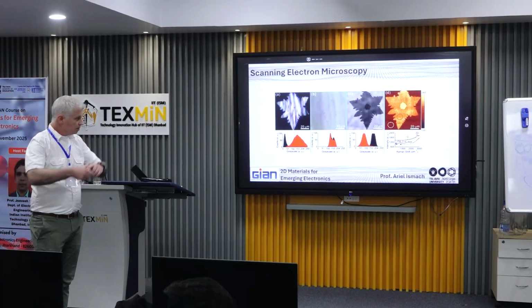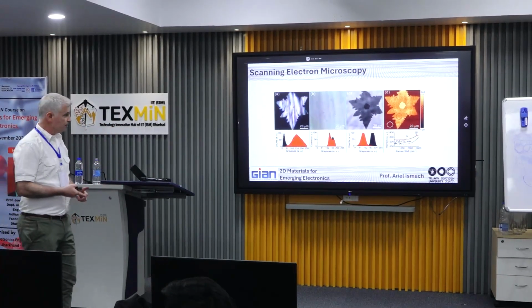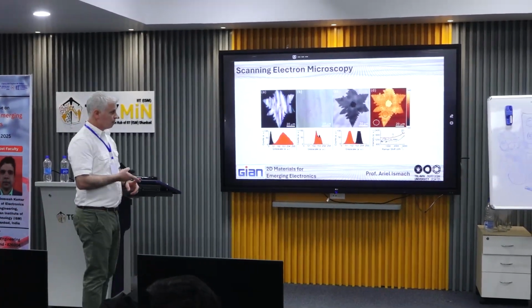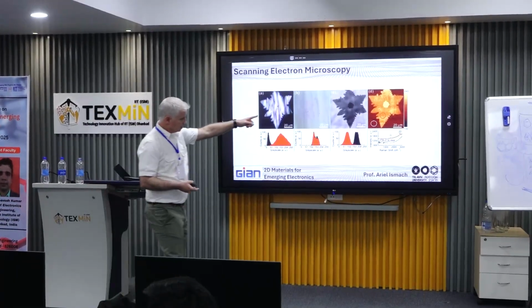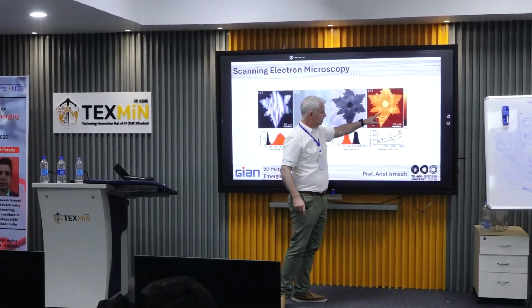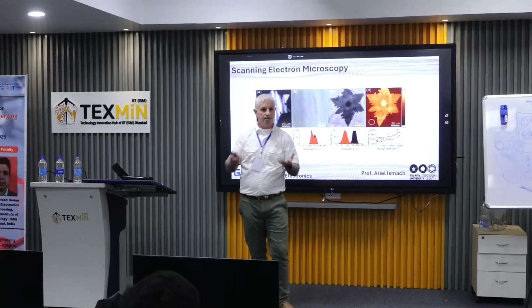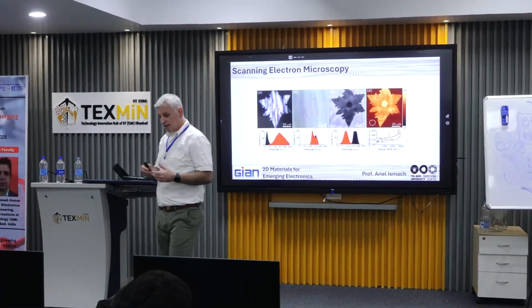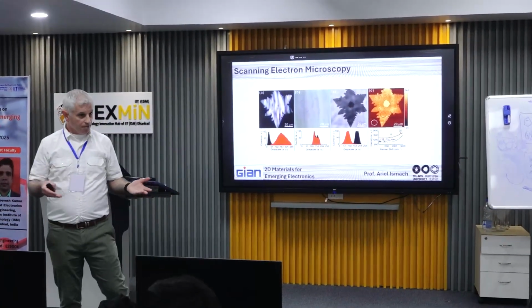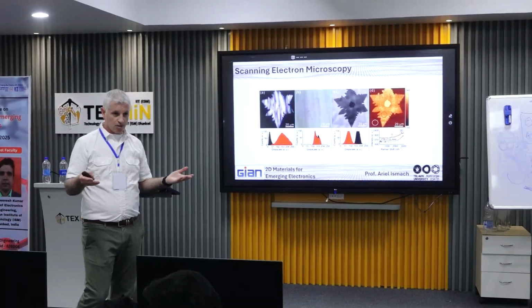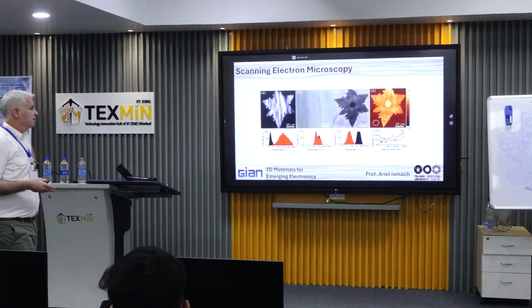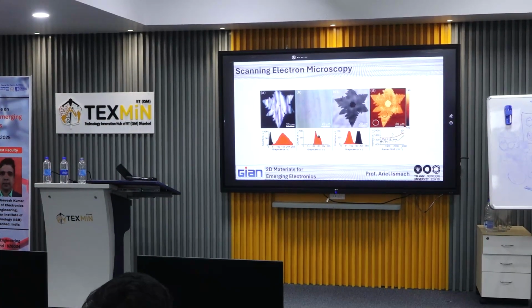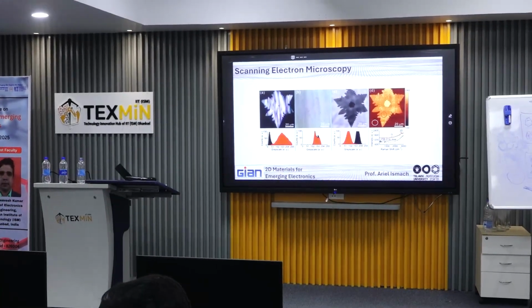It gives you the coverage, it gives you the number of layers, the bilayer and the single layer are very easily distinguished. It gives you the quality of the material, by seeing if we have defects, and the nature of the peaks in terms of the sharpness.